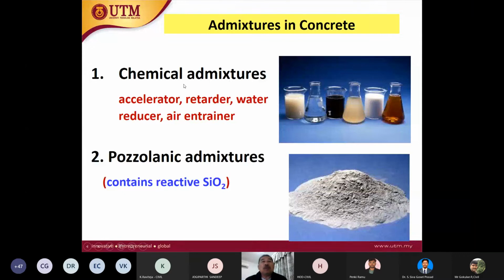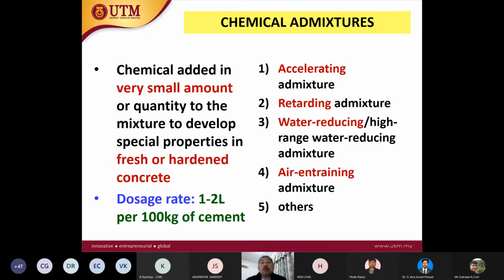So admixtures in concrete. So we have chemical and also we have pozzolanic. Pozzolanic we use to replace part of the cement content. Admixtures, for example, retarder. So this is used for the ready mix batching plant to transport. So pozzolanic material, example of fly ash, silica fume, it contains reactive silica that reacts with calcium hydroxide from the hydration process of cement, producing more CSH gel. Again, the formation of CSH gel is very important in our concrete to ensure that the concrete is dense.